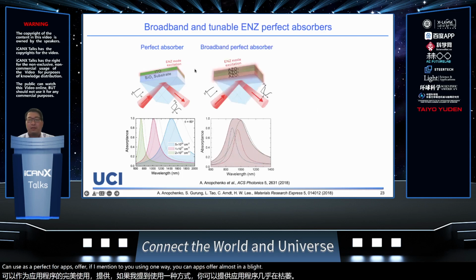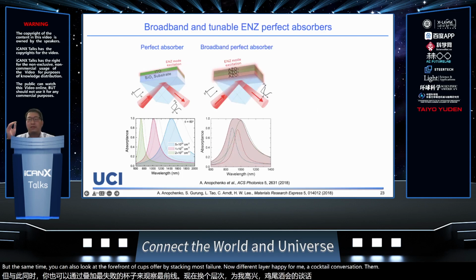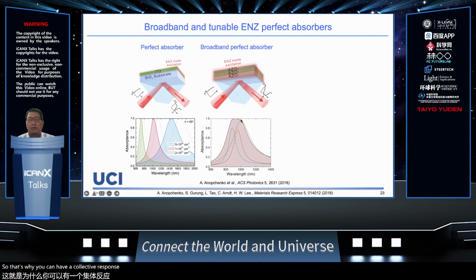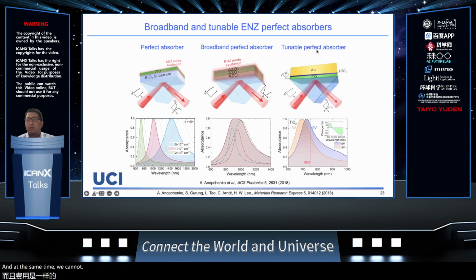But at the same time, you can also make a broadband perfect absorber by stacking multiple layers. Different layers have different carrier concentrations, which means different ENZ wavelengths. So you can have a collective response, giving a broadband absorption in this case. At the same time, we can also use the tunable mechanism I mentioned. By applying a voltage, we can tune this absorption band to different wavelengths, with a modulation of more than 100% in the absorption.